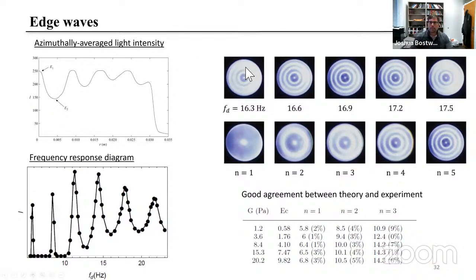So you can see resonance developing in the right image here as we change the driving frequency from 16.3 hertz to 16.6 to 16.9, where resonance actually occurs. This is defined by the sharpness or blurriness of the image. For the 16.3 hertz image, the image is very blurry and the wave pattern is not a typical standing wave, but rather a traveling wave. Whereas for the driving frequency of 16.9 hertz, the pattern is very clear and very steady.